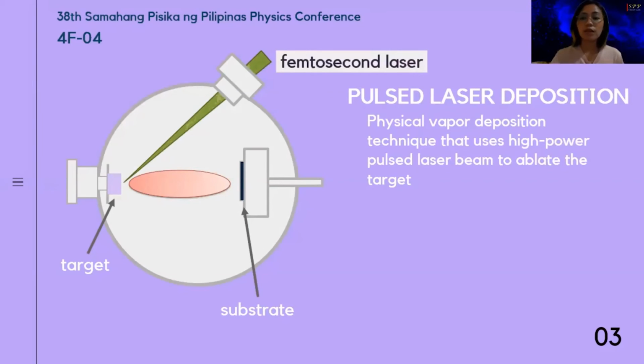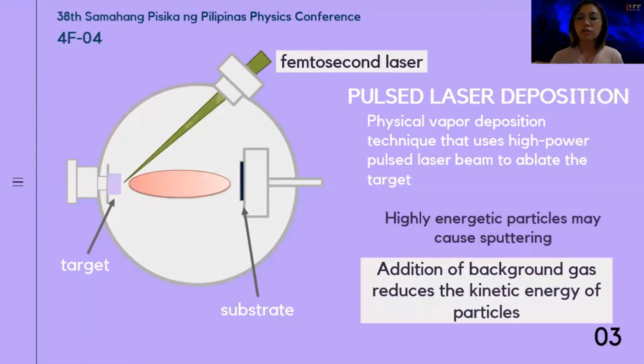In this experiment, we use a femtosecond laser, which emits optical pulses in the domain of femtosecond. This produces highly energetic particles. These highly energetic species ablated from the target may cause damage to the surface by sputtering and may cause defect formation in the deposited film. The introduction of background gas eliminates this phenomenon by the addition of collisional processes. The kinetic energy of the ejected particles is reduced upon interaction with the background gas, and this allows the growth of particles with low energy on the substrate. Several parameters affect the properties of deposited materials, which include the type of background gas used as well as its pressure.